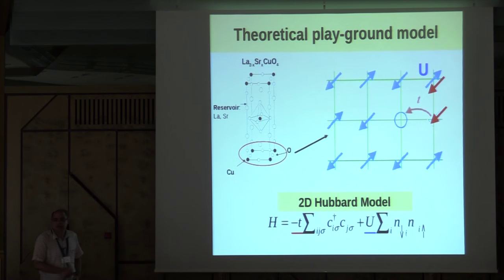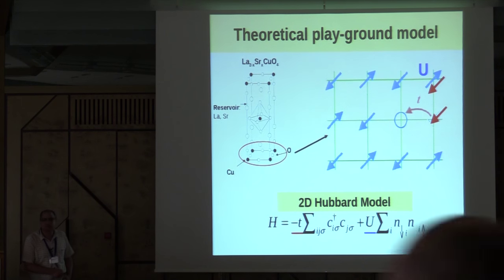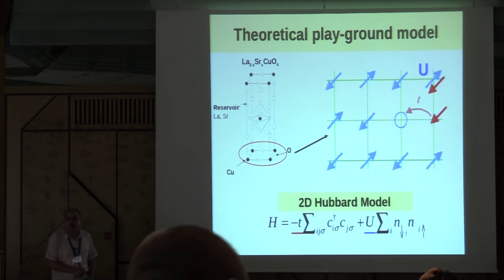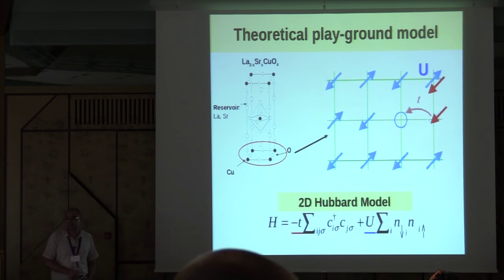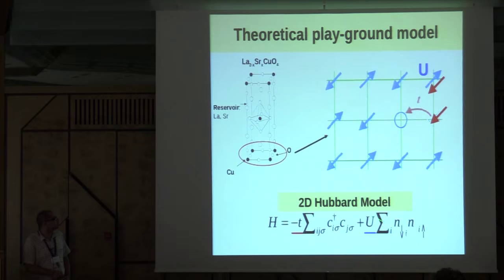So we have a square lattice in 2 dimensions. The situation which is interesting is the following, where you are close to the Mott insulator, which means you have 1 electron per site. In that case, the interaction, this term U, that is active when you have a double occupation of the sites, kicks in and penalizes the system enormously. So when you have a situation in which U is of the order of the kinetic energy, the system is fighting between leaving 1 particle per site and moving particles around.